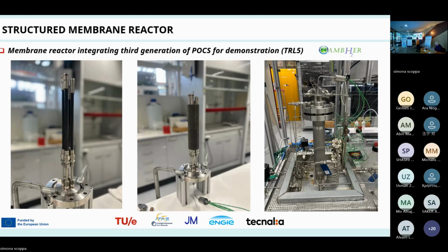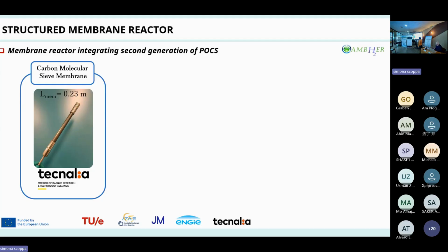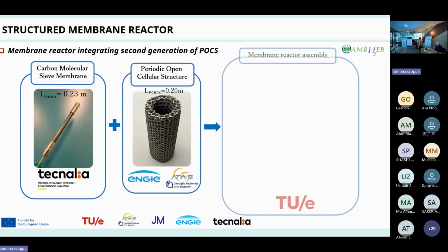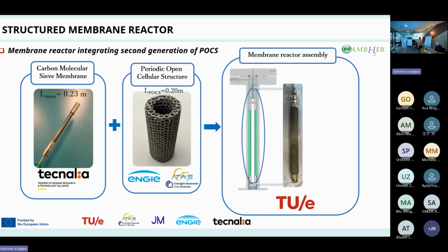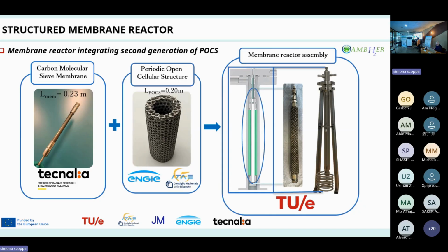And we have established the structured catalyst integrated with the membrane prepared by Tecnalia, integrated with ENGIE, and this is the reactor, and the activity is in progress. So we have no data on this actually, but basically this is the final configuration for a demonstration. You can see that in this case, a gyroid catalyst is integrated with the four membranes. But I can give you some data on the single tube membrane reactor obtained with the second generation of catalyst.